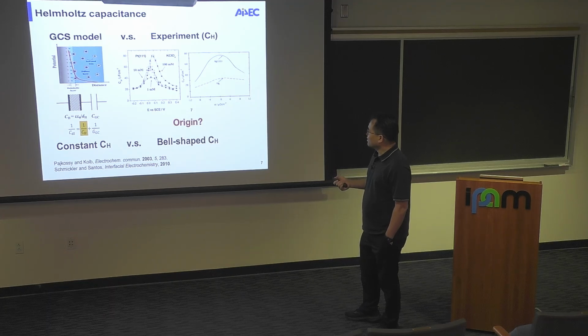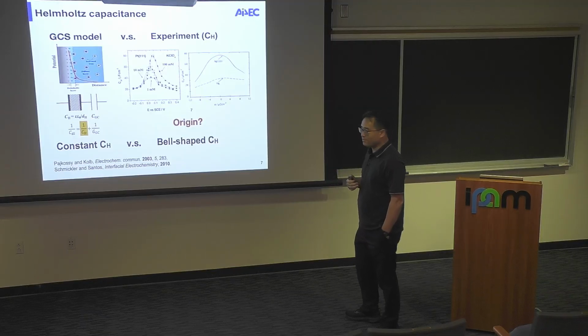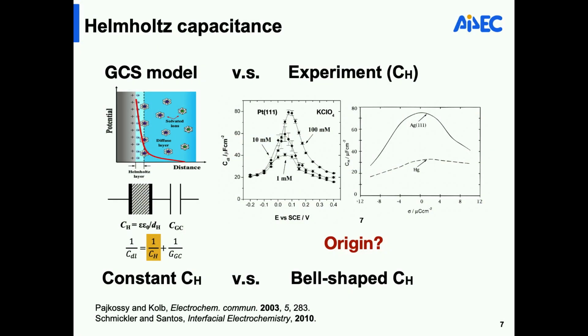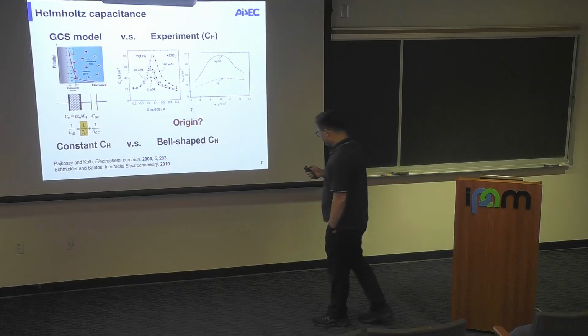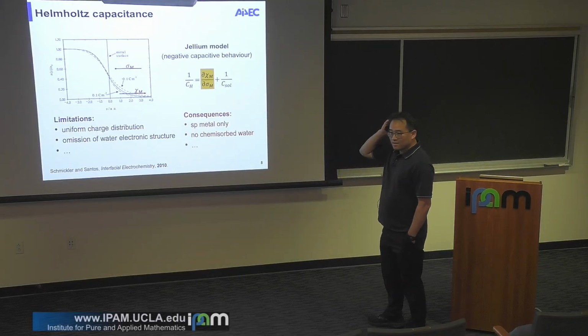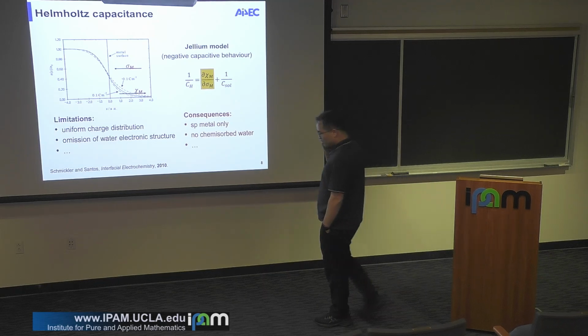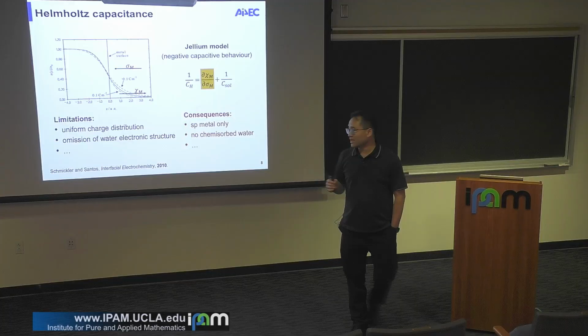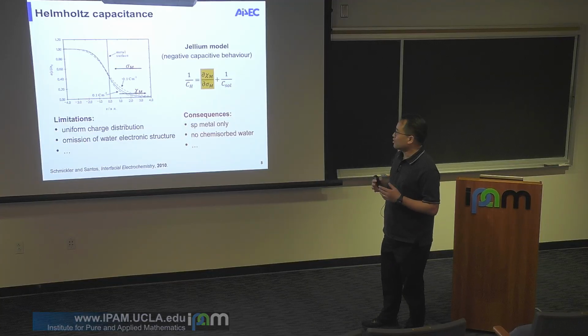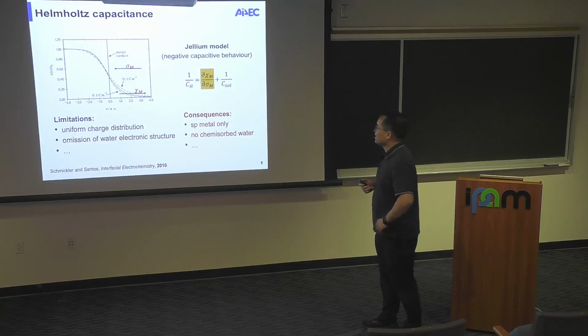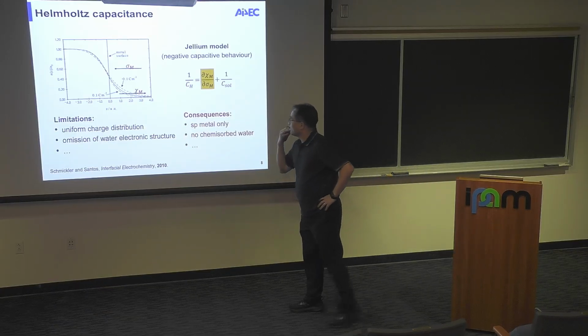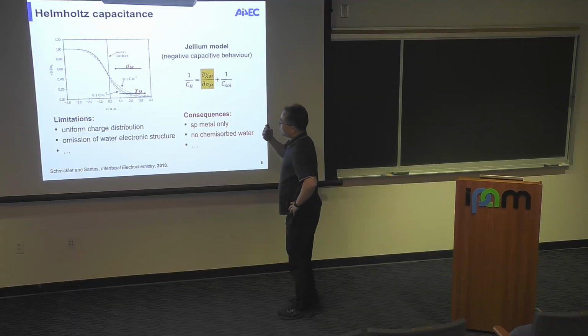From experiment, you can show lots of metals show this so-called bell-shaped Helmholtz capacitance. You have a maximum near the potential of zero charge, actually slightly more positive with respect to the potential of zero charge. Platinum, silver, all the same. In the field, that was noticed many years ago by Trasatti and also Schmickler. I think this is related to the electronic structure of the metal electrode. So something, and they apply this jellium model to explain this, right?